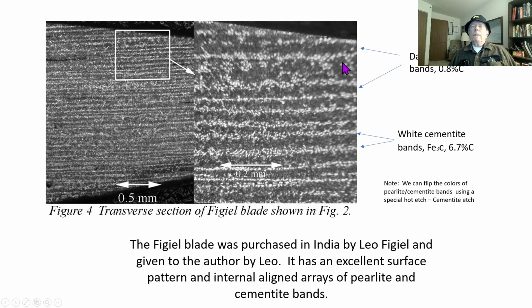pearlite, which is iron matrix with plates of cementite in it, average composition 0.8% carbon, etches black. The other constituent, which is beautifully lined up as well, is iron carbide. It etches white. It is called cementite, composition 6.7% by weight, 25% by atomic.